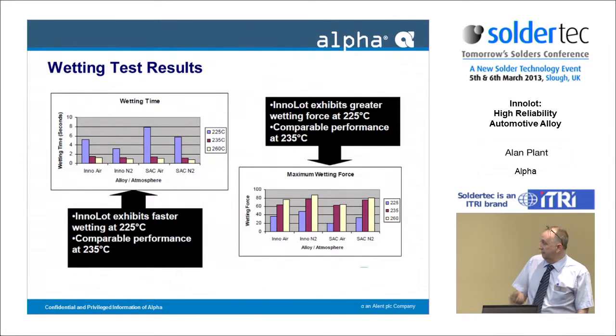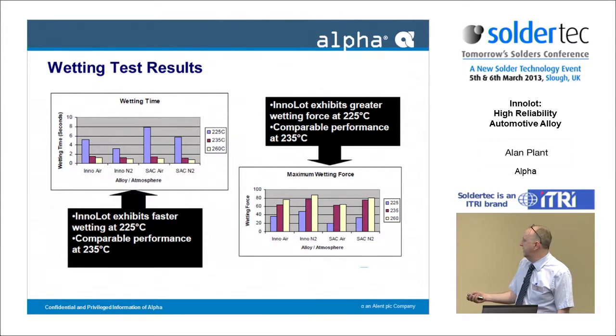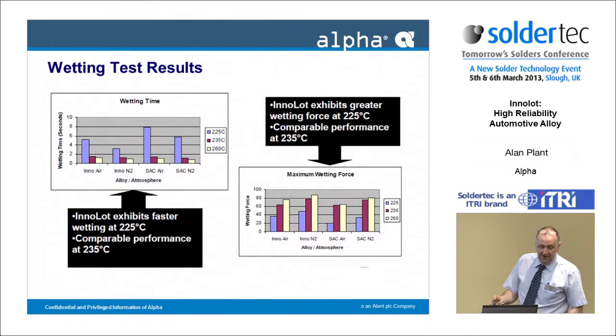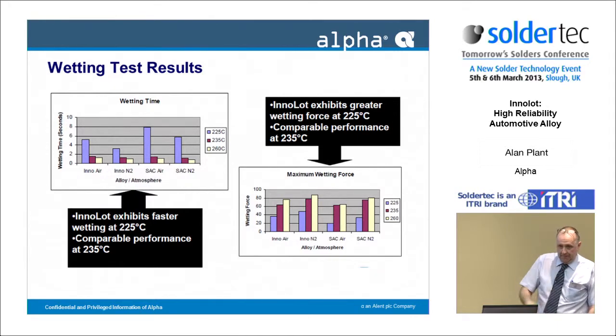Tabulated, it's not particularly easy to see or look at. The most important thing is the graphical form of the temperatures. That's what we're looking at, the wetting results. So 225 compared to 235. The SAC alloys, you can see at 225, take a long time to wet. The degree of superheat over the melting point is not that great really. So the Innolot does show the potential to wet at that temperature and have a wetting force. So that's doing it from a wetting balance test point of view.